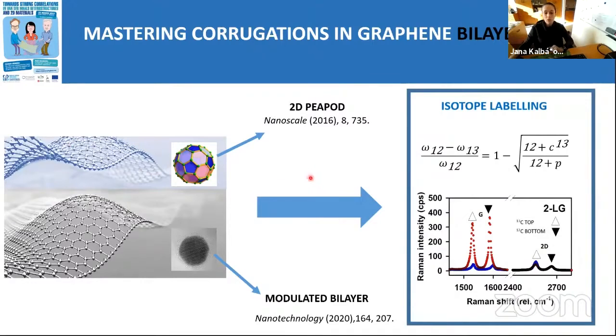Because we are mostly looking at phonons, we can simply color one of these two layers. So we can engineer the lattice in a way that we replace the atoms by atoms of a different mass. As a consequence, the phonon frequencies will change, and then we can very conveniently address those two layers within our experiments. So instead of using two carbon-12 layers, we are using carbon-13 and carbon-12, and we can then nicely detect those two layers separately in the Raman spectra, as shown here. These are representative spectra in the area of the G and 2D modes. I'm not going to talk in detail about where they come from, because I believe this is very well known. But it's important to mention that we can nicely trace the top and the bottom layer separately with our approach. So why is this useful?